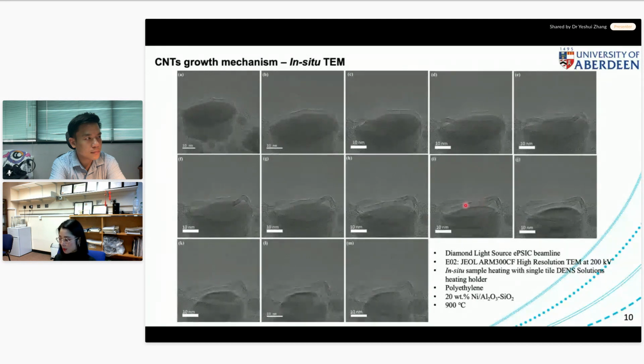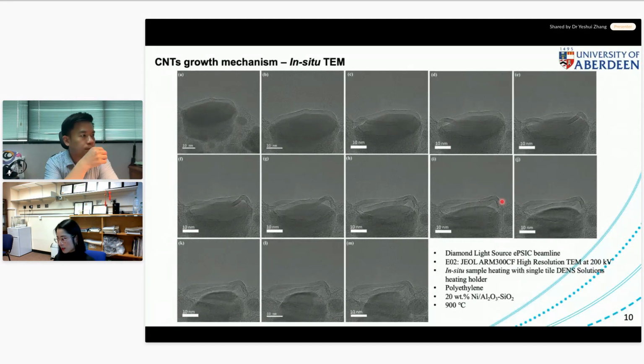The diameter has been fixed because, based on published work, the diameter of these carbon nanotubes will be dominated by the size of this catalyst particle. And the length, if you see the length between the top layer of this tube and the bottom, has been extended.